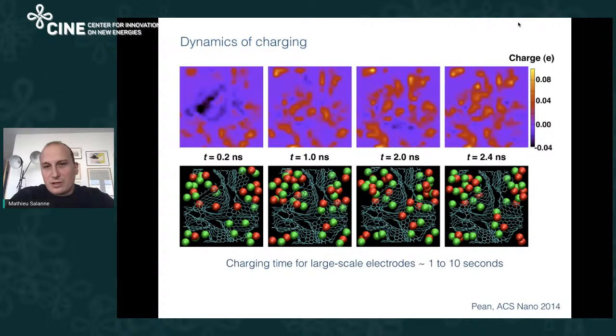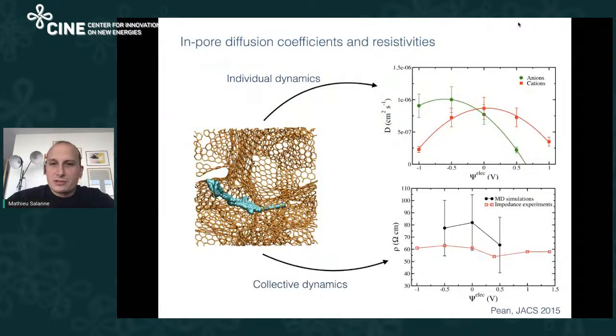And this is when you start to have larger charge. But in the end, you still have a large diffusivity. And this is something that we have studied in a further study by computing the diffusion coefficients. And here you have values of diffusion coefficients depending on the potential.